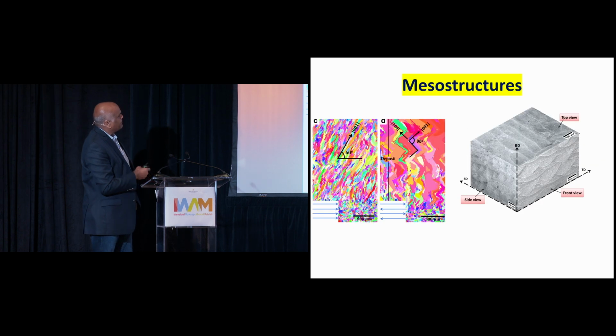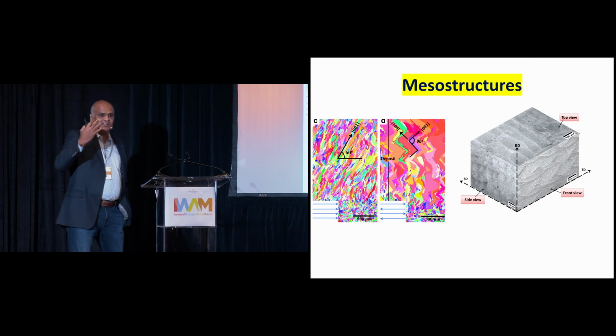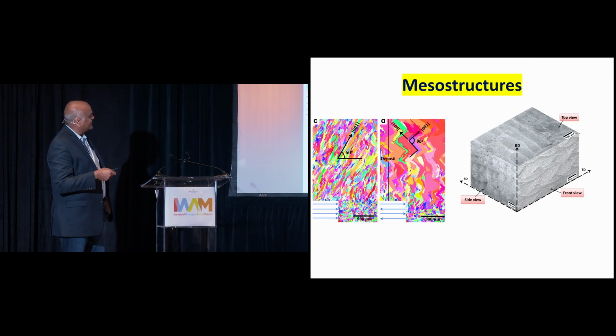Now if you zoom further out to a much larger scale, you get meso-structures. These are hundreds of microns in size. Here, for example, you can see the scanning is all in one orientation, and the grains seem to be all textured in 001 orientation, at about 60 degrees to the scanning direction.